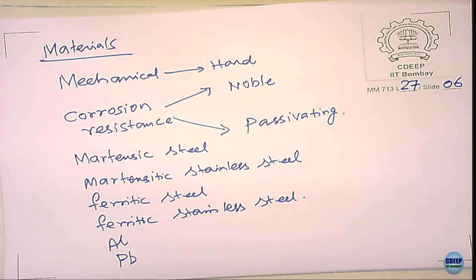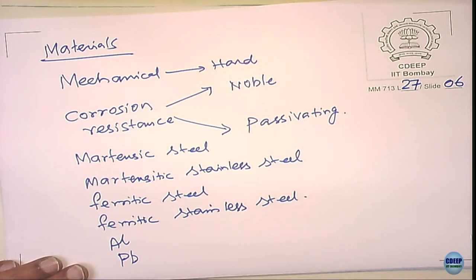Aluminum and lead, of course, if there are low velocities, we have fewer problems; when velocity is increased, then it is a problem. See, this is a very interesting thing. It is not necessary that you can extrapolate at all velocities. At a normal velocity, it is possible that lead, for example, in dilute sulfuric acid at static conditions, at very low flow conditions, may be good. Whereas with a high velocity, lead is softer, so that fellow will not even withstand that.